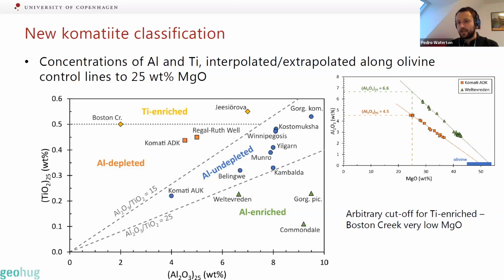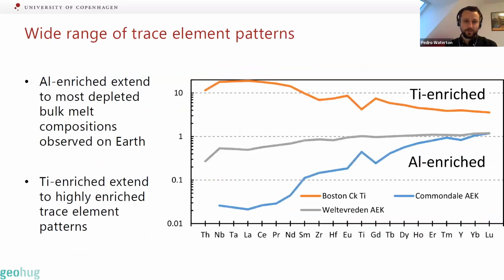And you can see here that when we compare aluminium-depleted komatiites from the Komati Formation in Barberton in the Kaapvaal Craton and aluminium-enriched komatiites from Weltevreden, there's actually no difference in the absolute amount of aluminium. It's just that all the Weltevreden samples have a higher MgO. And the big thing there is that the aluminium-enriched ones have much, much lower titanium, sorry. Okay,